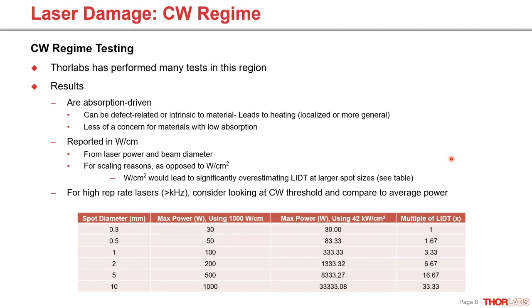And just something I do want to keep in mind is that for higher rep rate lasers, and here we're typically talking about a kilohertz rep rate or above, you might want to consider just looking at the CW damage threshold if it's available and comparing it to the average power of the laser, because as you can imagine, you will see similar heating behaviors. Just because, as the laser comes in at repeated pulses at a high rep rate, that does tend to produce a similar thermal load to a CW beam. So something to keep in mind.